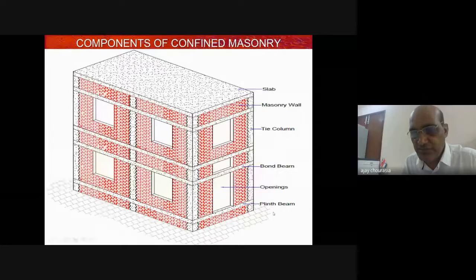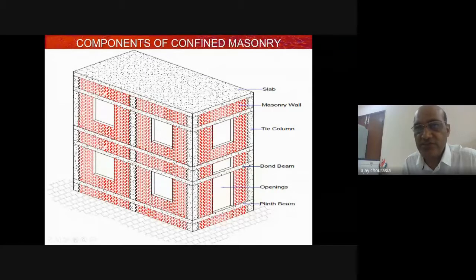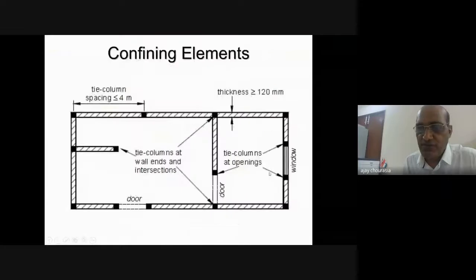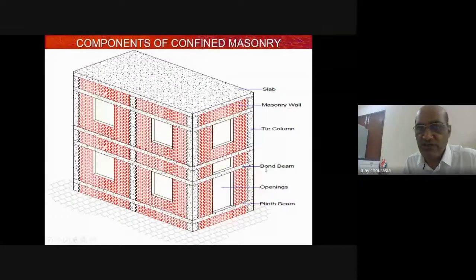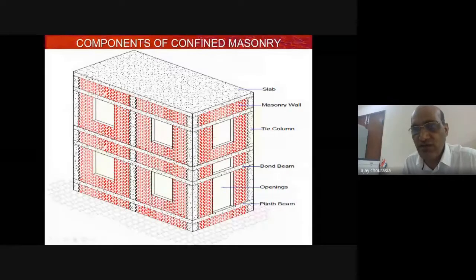These are basically the components of confined masonry buildings when constructed. It is basically the plinth beam or bond beam at the lintel level and roof level. If you have an RC slab, then there is no need for any beam at the RC slab level. Then this vertical element is the tie column. Then this is the bond beam and this is the slab. Apart from that, you can see in this picture that additional grooves have been provided, and this toothing you have to provide maximum to the tune of 40 mm, ranging from 25 to 50 mm.